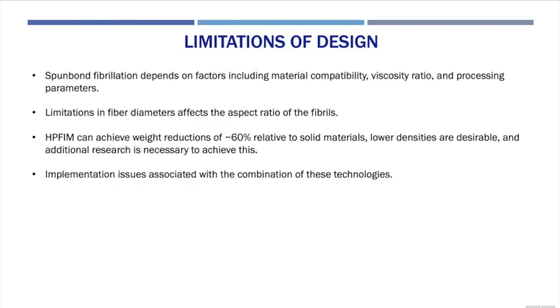The second issue is the actual implementing or inputting of the fibers into the injection molding machine. In many cases, it is necessary to add an intermediate step to make a master batch of fibrillated pellets and then implement those pellets into the injection molding machine. This will help smooth over the transition and facilitate a faster process.